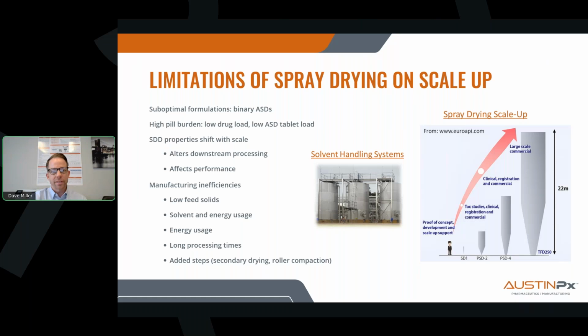Spray drying systems are sensitive to parameters like feed solids concentration, mode of atomization, residence time, et cetera. And with those changes, the particle size distribution and morphology of the particles can change. That in turn can alter downstream processing and sometimes biopharmaceutical performance. And not to mention that a lot of the feed solutions for the SDD processes that we've seen lately are typically very dilute, low solids concentration. So this requires enormous volumes of solvent per kilo of SDD. And this also translates into long processing times and substantial energy usage.